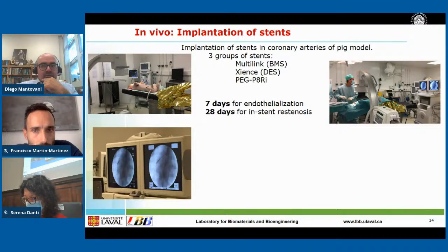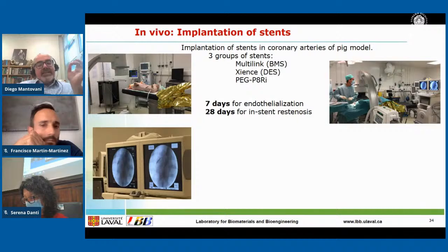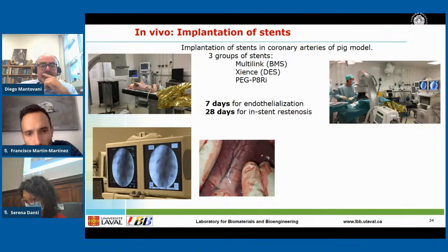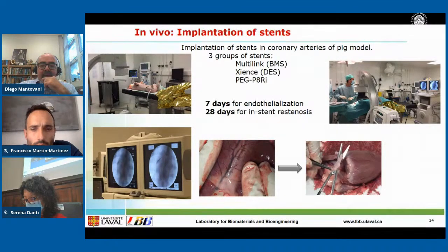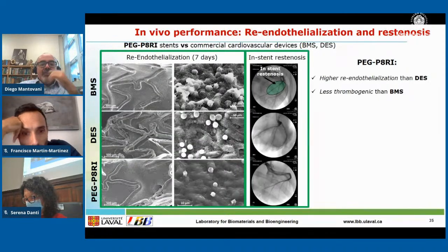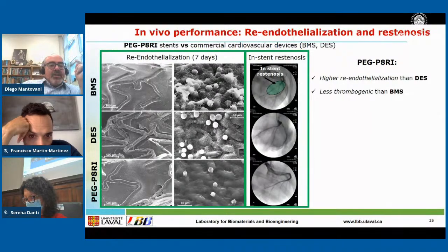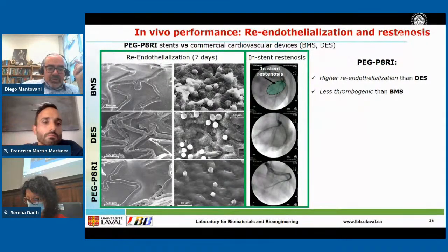So we were implanted for 7 to 28 days, mainly because the idea of PEG-P8RI is really to check the rapid endothelialization boosting effect that is provided by the presence of the peptide. This is the stent once implanted in pig, and this is during explantation, and finally we collect materials to go for further analysis. And these are the very interesting results. You have a bare metal stent, you have a drug-eluting stent, and here you have the peptide-grafted stent.